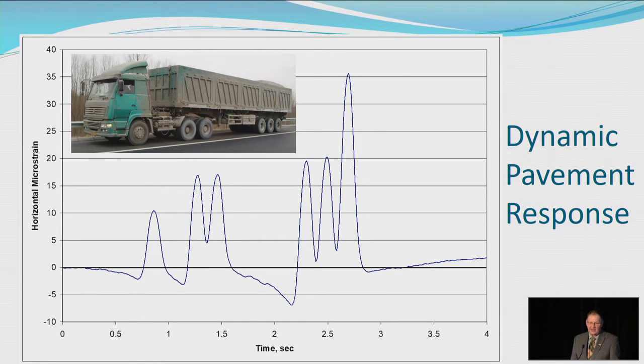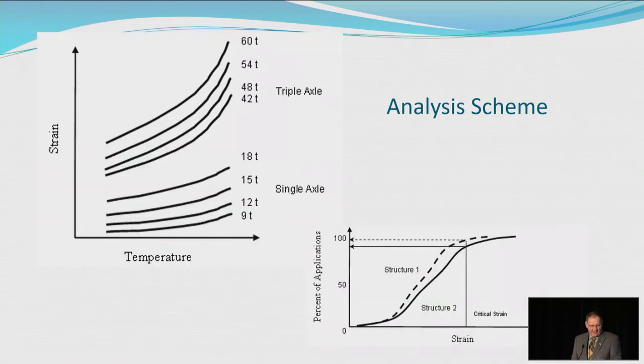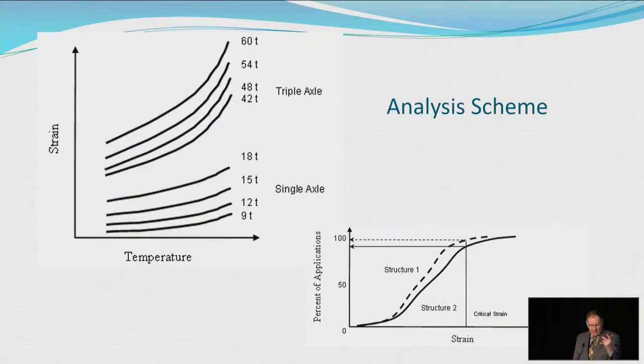That truck had 60 metric tons of aggregate on those 3 back axles. And the idea was that you can see there where it says triple axle and 42 tons, 48, 54, and 60 tons. Those are conceptual lines, by the way. That is not data that you're looking at. But the idea being you would expect to see as the load goes up, of course, that the strains go up.